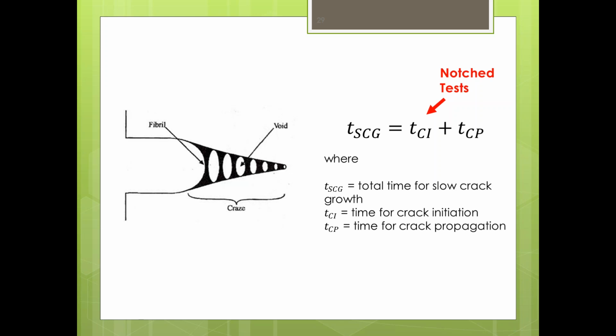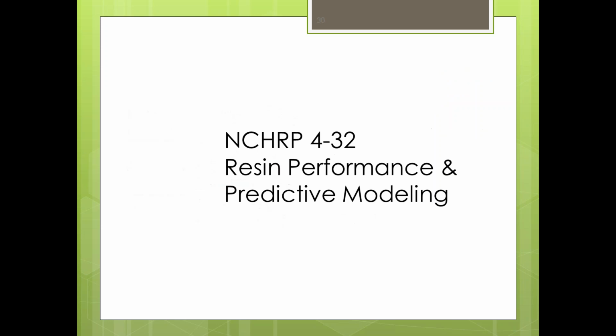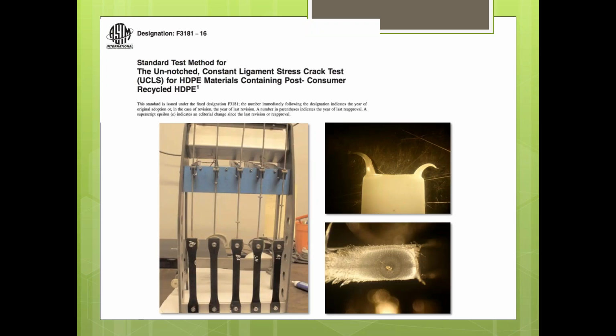With recycled plastics, obviously the big concern is contamination still existing within the blend in the resin itself. So how can we adequately measure contamination and assure that even if there is contamination in the plastic, that it's not going to turn into a propagating crack that's going to lead to additional stress cracking and embrittlement and ultimately failure long term. And that's what the first NCHRP 4-32 research report was geared around, that resin testing piece and the predictive modeling aspect after that.